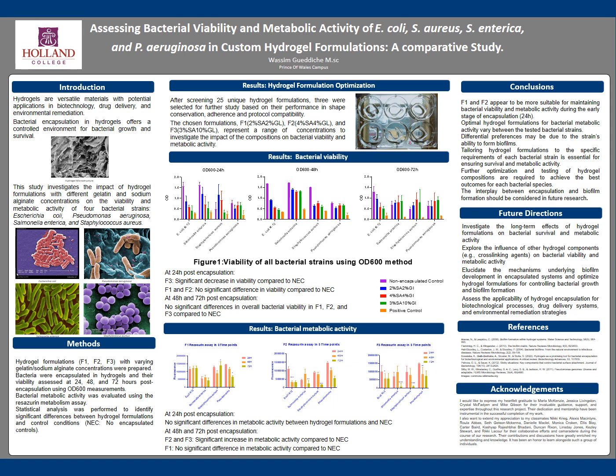F2, and F3. At 24 hours, there were no significant differences in metabolic activity between the hydrogel formulations and the non-encapsulated controls. However, at the 72 hours time point, F2 and F3 showed a significant increase in metabolic activity compared to the non-encapsulated controls, while F1 displayed no significant difference.